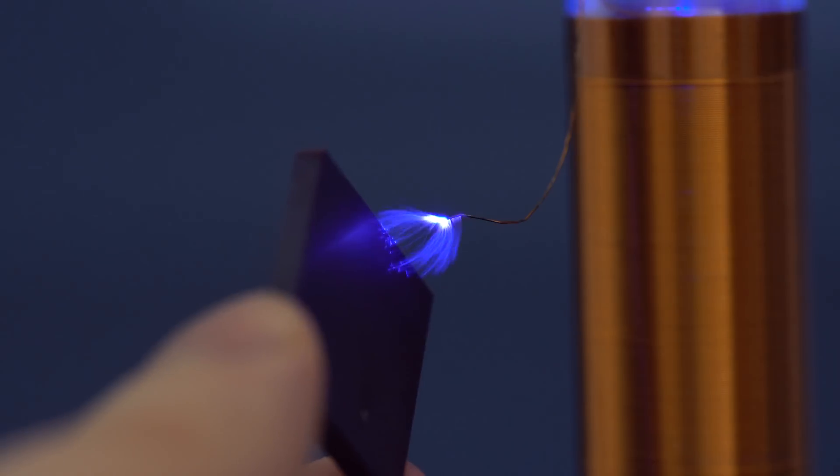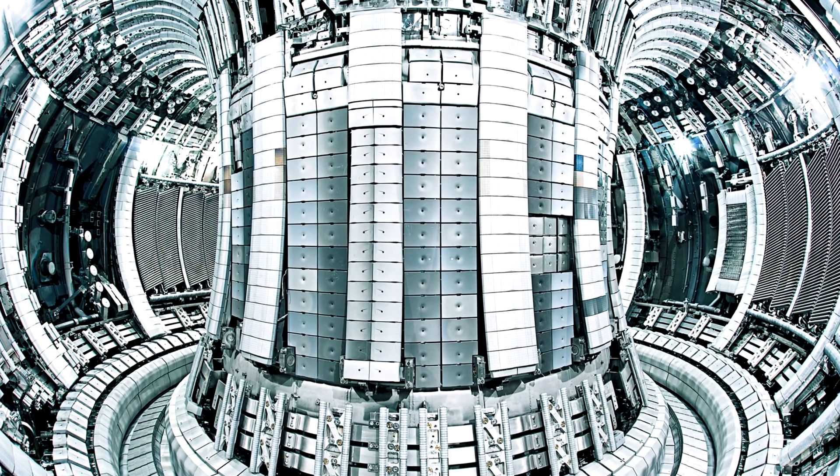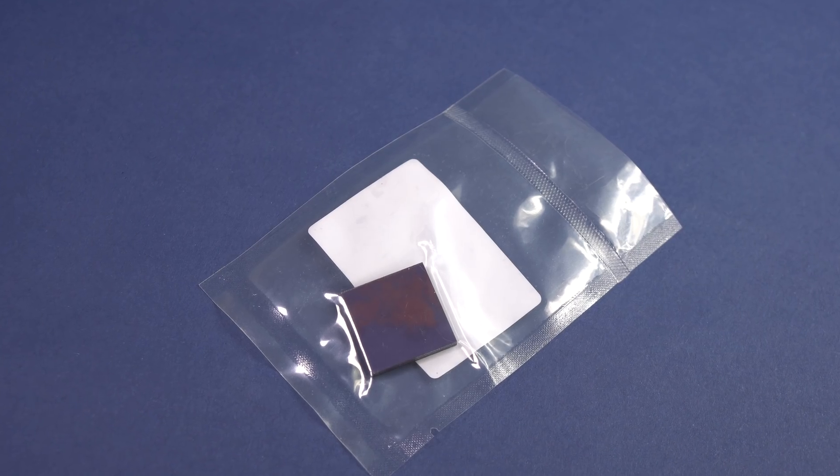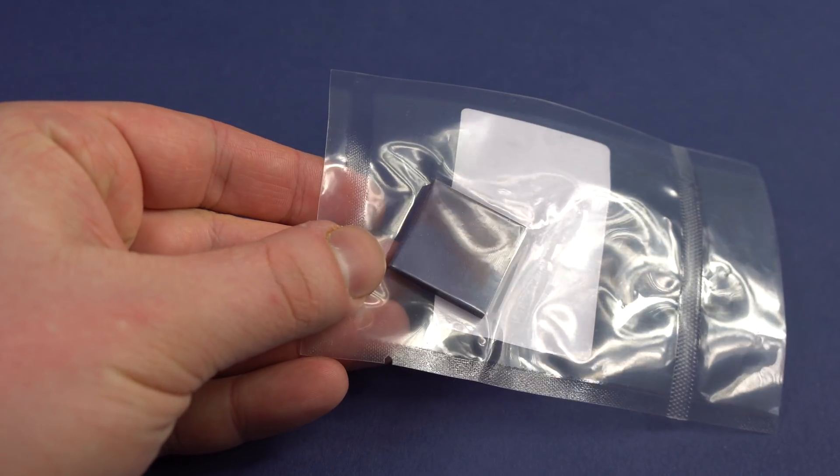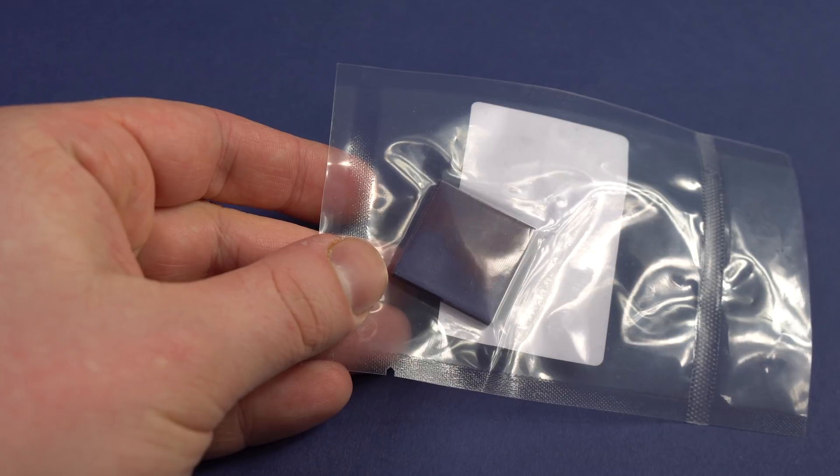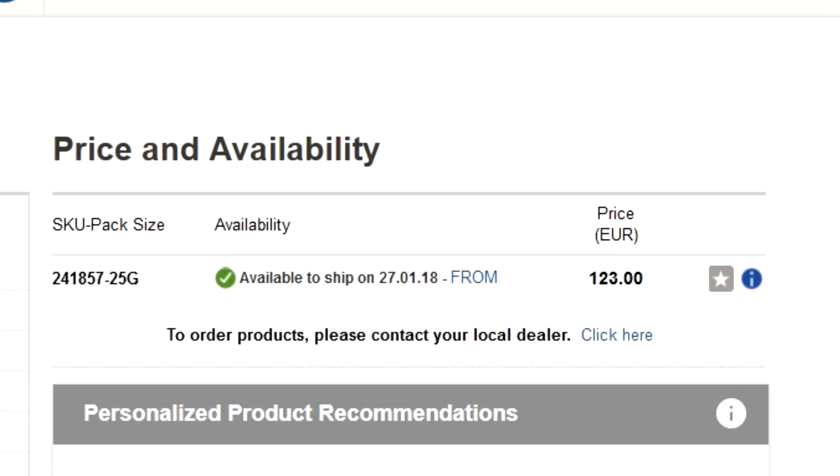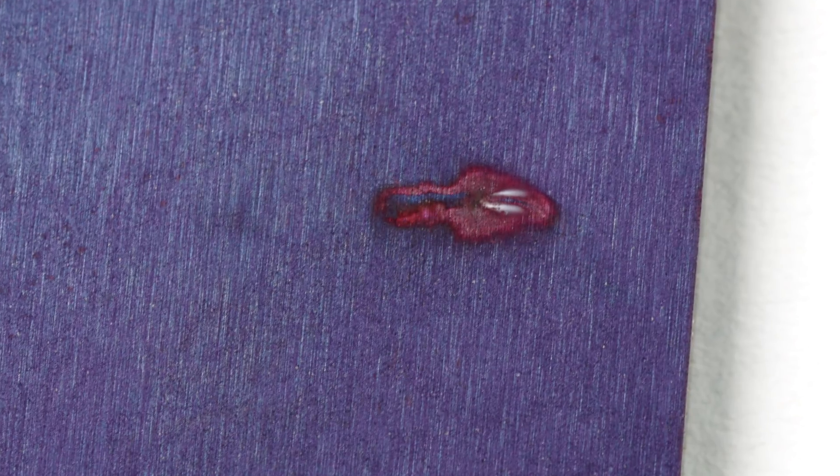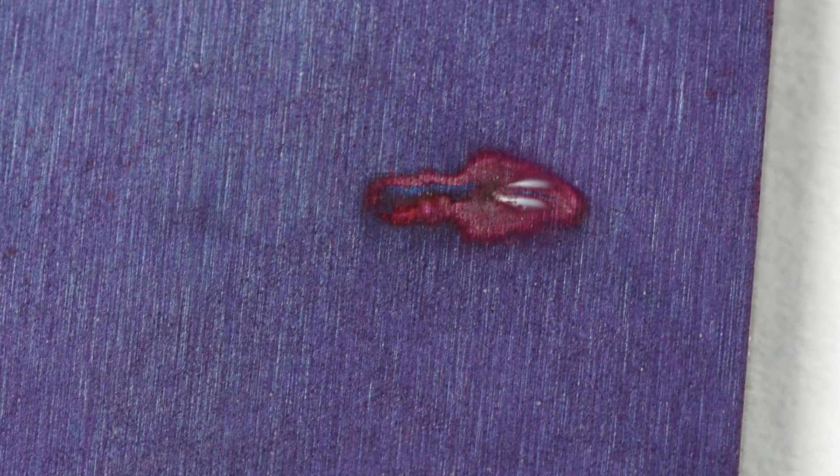In the future, this material may substitute such refractory metals as molybdenum or tungsten in fusion reactors, but it's not that easy. Lanthanum hexaboride's unique properties come at a high price. It is expensive to extract and difficult to bake and shape, making it a quite expensive material. Lanthanum hexaboride is extracted by electrolysis of lanthanum trioxide with borax and by collecting the extracted hexaboride with graphite cathodes.